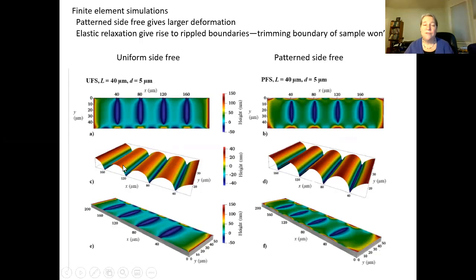Sure enough, if you just look at the middle, we see the same type of structures that they saw in the experiment. But if you look at the whole sample, there's a lot of relaxation happening because of elasticity at the edges. So there is a mechanical constraint that this very thin elastic film is attached to a substrate, and we don't allow it to debond in the simulation, nor does it debond in the experiment. But there are displacements. You get kind of a rippled edge that comes from displacements actually in the plane, not even just out of the plane.